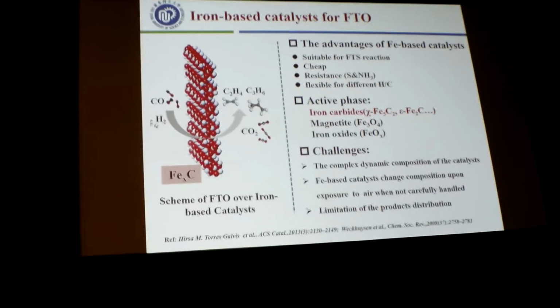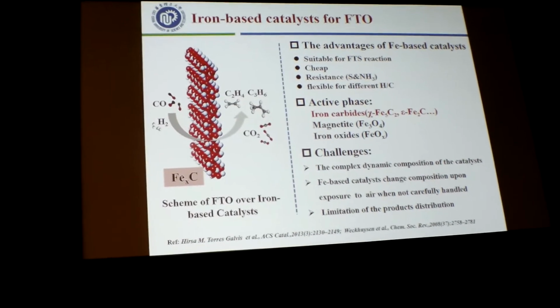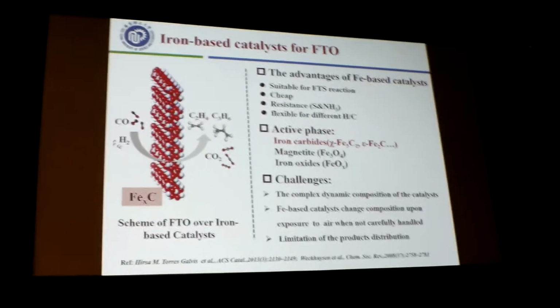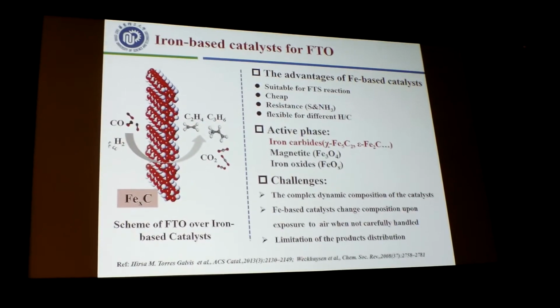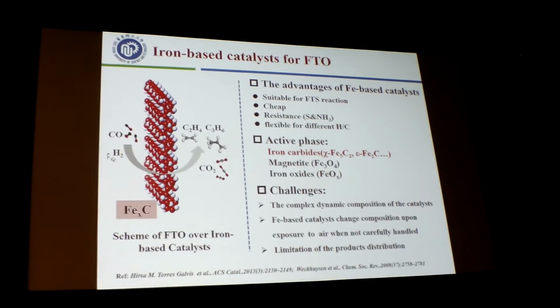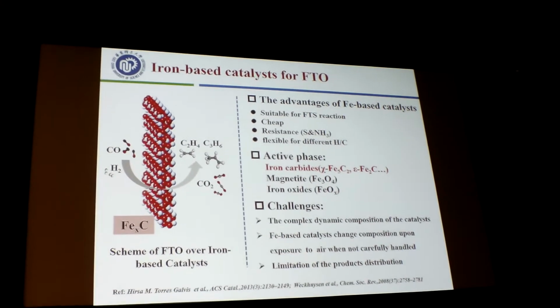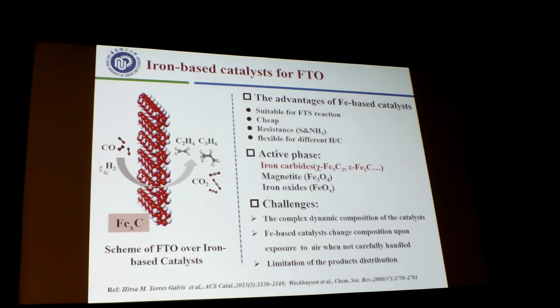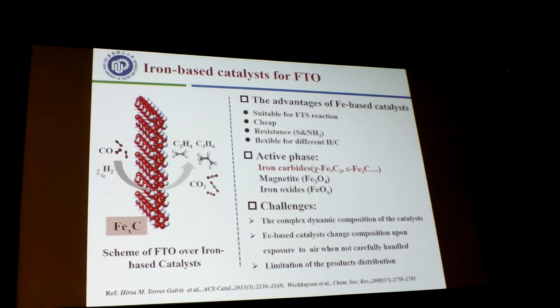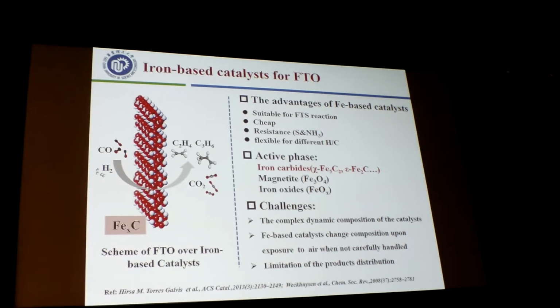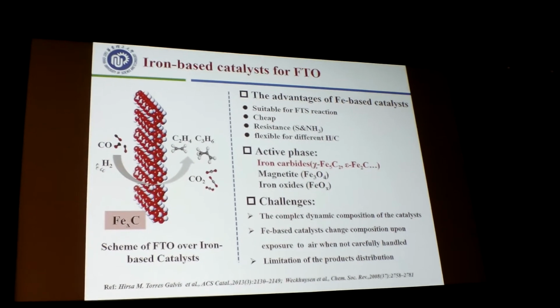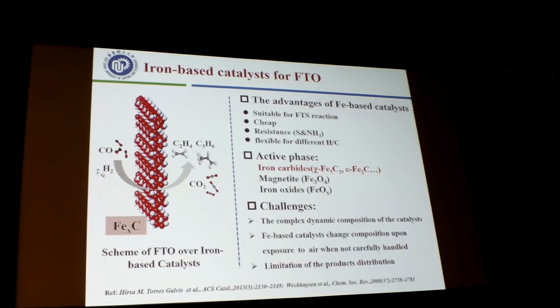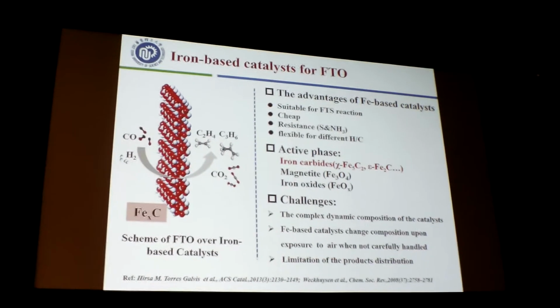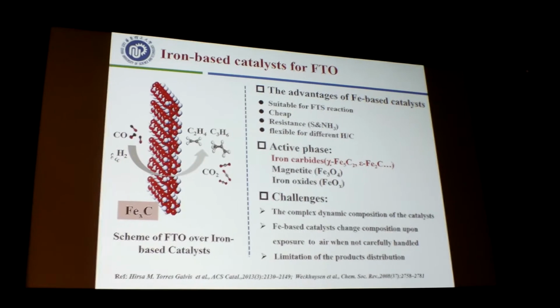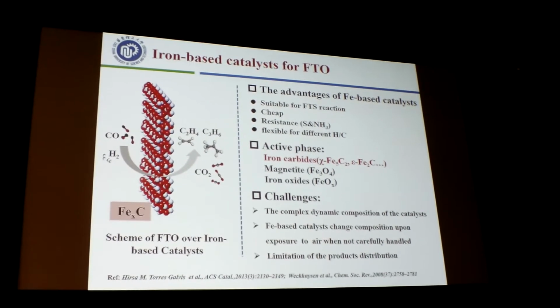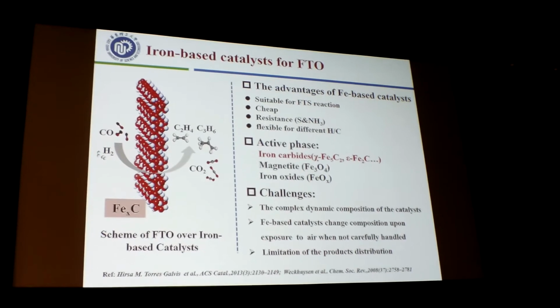But there are also challenges, since the iron catalyst undergoes very complicated phase changes during activation, reaction, and deactivation. So it is very difficult for us to identify the nature of the active phase, and this also poses challenges for iron-based catalyst design.